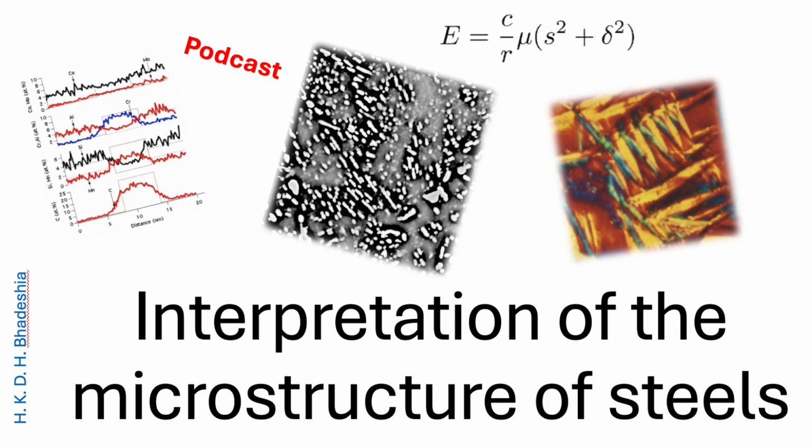Exactly. It forms those characteristic thin wedge-shaped plates because of that high strain. And to manage that strain energy, the phase often grows as two back-to-back self-accommodating plates at the same time. And what does that do to the structure? It relieves the strain locally, but it tends to result in a much coarser, less desirable microstructure overall.